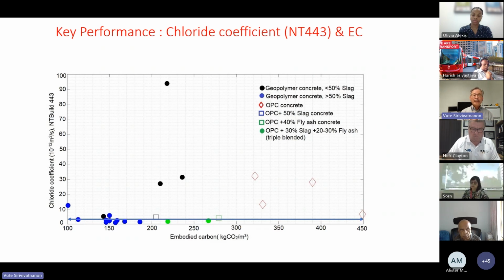Now, if we look at the durability, in this case in terms of chloride coefficient, again, this is from the NordTest NT Build 443, which is an accelerated chloride diffusion test method. You can see that for the sort of level that we are looking for, a very low diffusion coefficient of around 4 to 8 times 10 to the minus 12 meters squared per second, only one type of geopolymer concrete is likely to give you the performance, and that is the blue color, which represents geopolymer concrete with more than 50% slag. Whereas the other concrete, the one with lower than 50% slag, although it gives the strength that you may need, gives a much higher chloride diffusion value, and therefore will not satisfy the durability requirements.